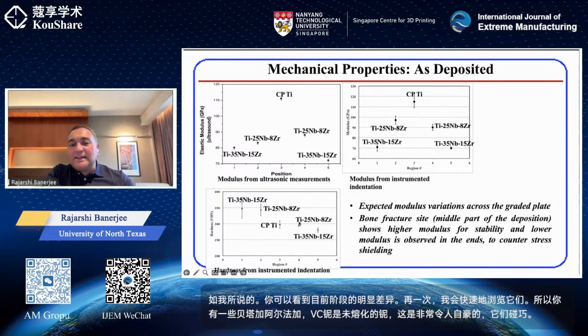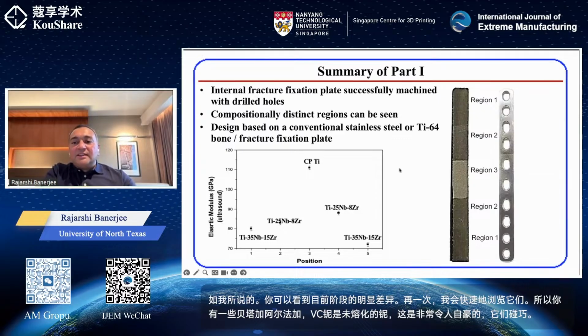In terms of the hardness gradient, it was not as much, which is fine because the mechanical strength of all these alloys is reasonably high for the purposes that we need. So it should be fine. The hardnesses were lying in the range of about 250, 270 to 350, which is fine for the application intended. So this is the summary, and on the side here, I wanted to show you that this original build was then further machined. We showed the proof of concept that we were able to drill these holes into these layers, maintain the mechanical integrity, and it was also mechanically finished or polished to form exactly like a fracture fixation plate would look like with this modulus gradient.